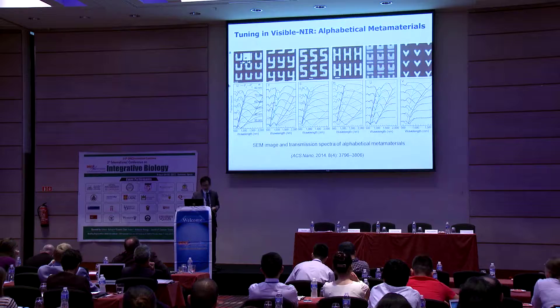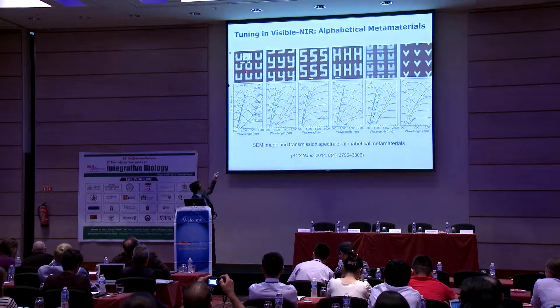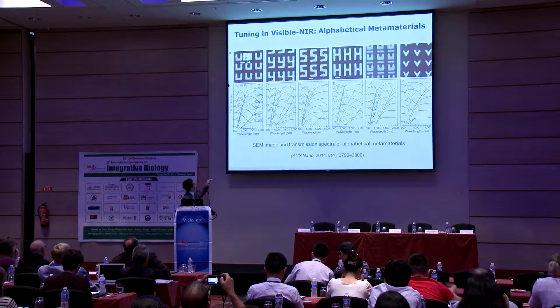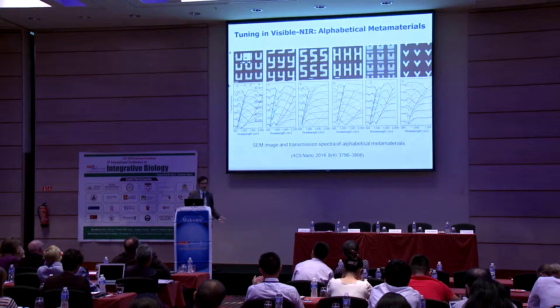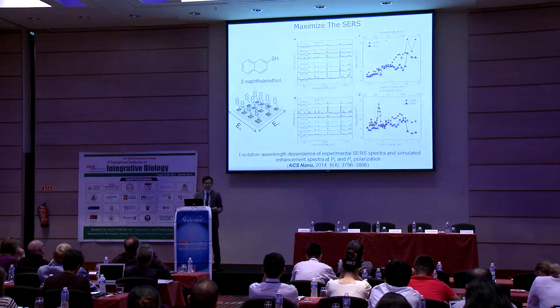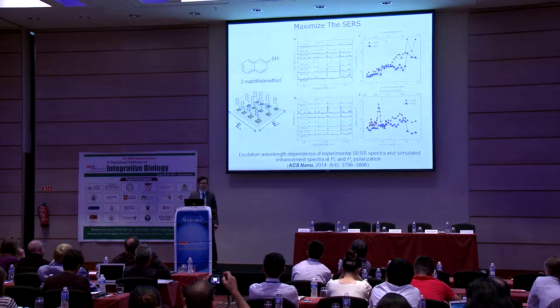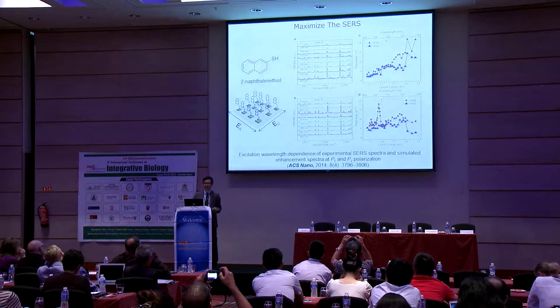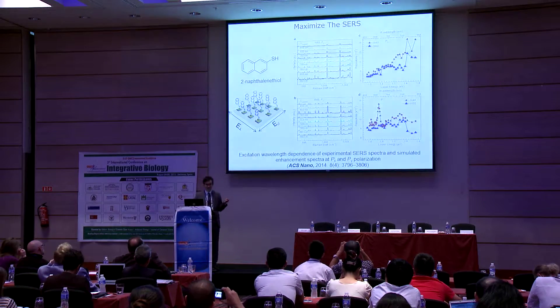Here is an example of how we can tune the optical response of the plasmonic metamaterial. We can fabricate metamaterials with different sizes and shapes — U shape, S shape, H shape, U-bar, and V shape — and also with different sizes to obtain a broadband optical response. Because Raman spectroscopy is a very weak spectroscopy technique — only one photon in roughly 10^8 to 10^10 scattered photons gives a Raman signal — people have developed substrates that can enhance the Raman scattering signal, including plasmonic substrates. The metamaterial can serve as a SERS substrate; however, to get the best signal, we need to optimize it so that the LSPR of that substrate is as close as possible to the laser excitation wavelength.